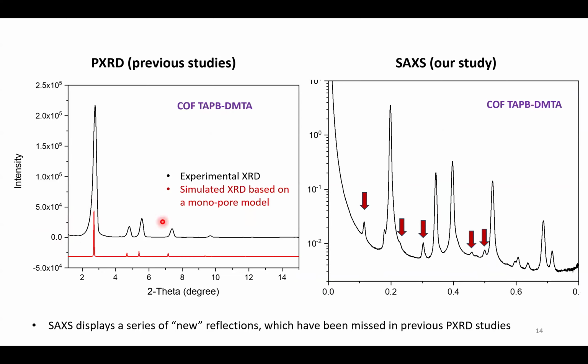Previously people didn't know the actual structure, so they didn't pay enough attention to the low angle region. And so in the XRD study, they missed the low angle reflections. Now, seeing that the unit cell is actually large, we conducted a small angle X-ray scattering measurement, because SAXS is more sensitive to the low angle signals. And indeed, in the SAXS pattern, we observe a significant peak in the low angle region, along with several new reflections that have been missed in previous studies. So this result in turn confirmed that our dual-pore model is correct.